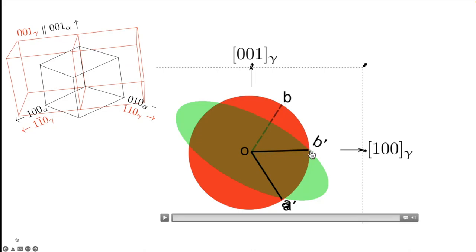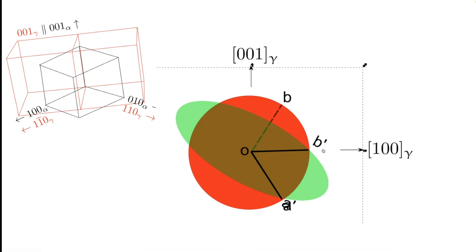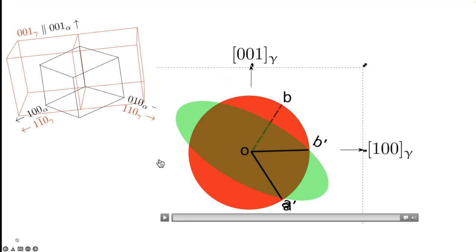But notice that this line goes further out of coincidence. So it isn't possible to produce two lines which remain coherent. In other words, it's not possible to find a completely coherent interface between the austenite and the martensite. And that, of course, contradicts what we observed with the shape change, which implied that there is complete continuity across the interface. Okay? So there's still something wrong,